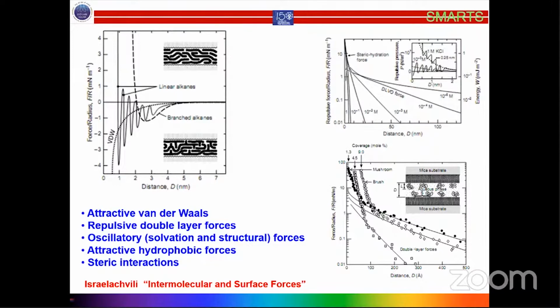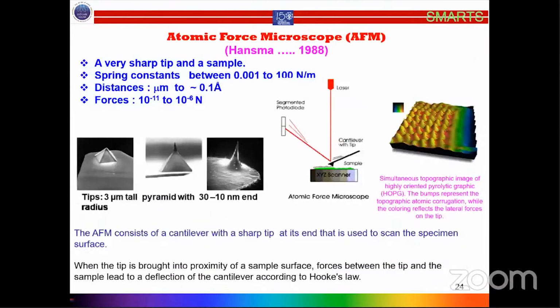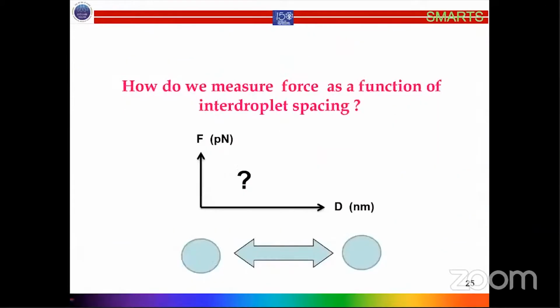Another technique that can be used to probe interaction forces down to 10⁻⁹ newtons is the atomic force microscope. It's again complex, but it's a simple system. The tip size can be of the order of a few nanometers, and you probe the forces between the tip and a macroscopic surface; a molecularly smooth surface is required. This is another requirement when it comes to forces down to the nanoscale. And here again, you can control the spacing and obtain the interaction forces. But in none of these cases can you probe the forces between colloidal particles which are suspended.